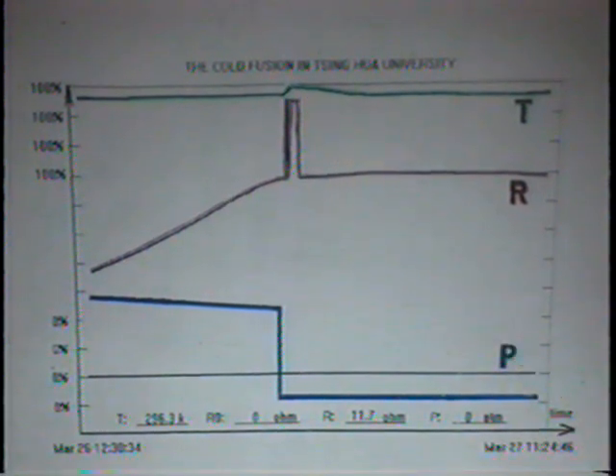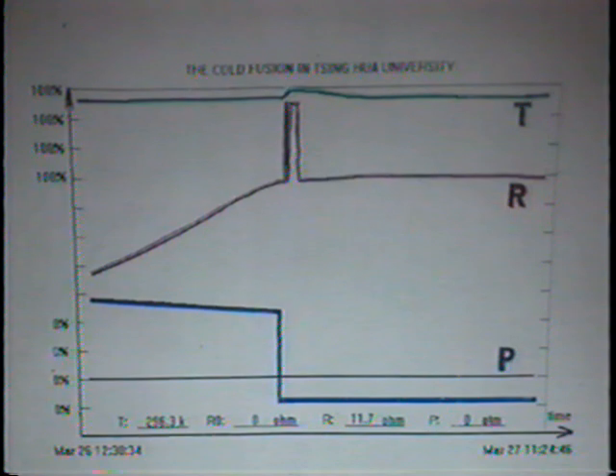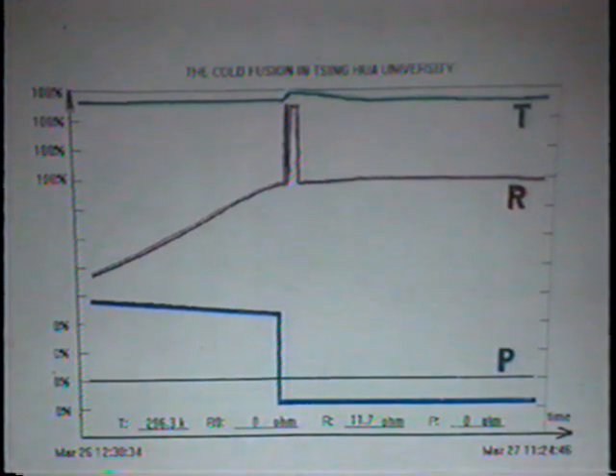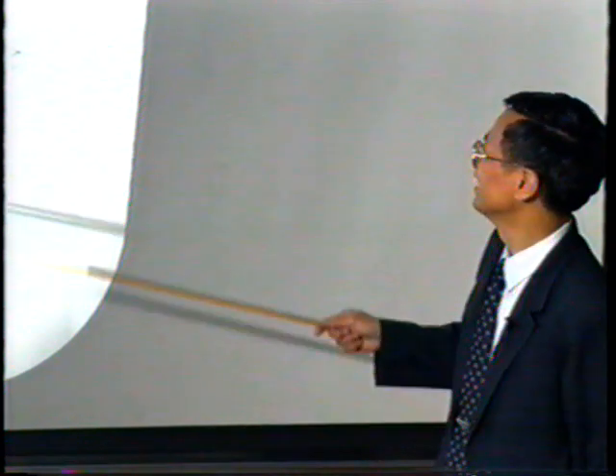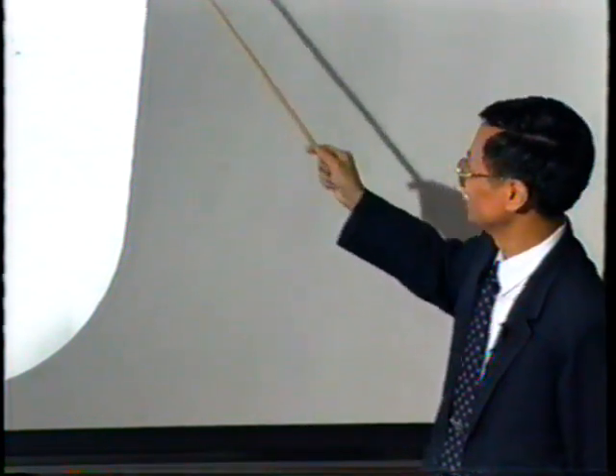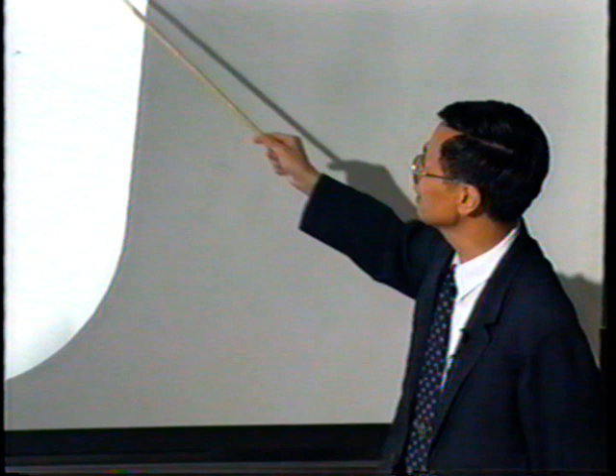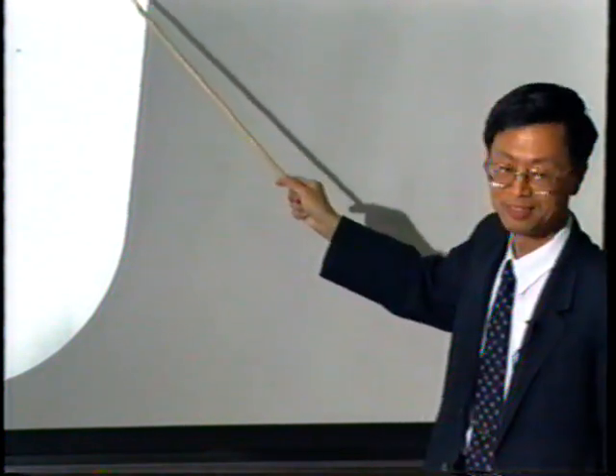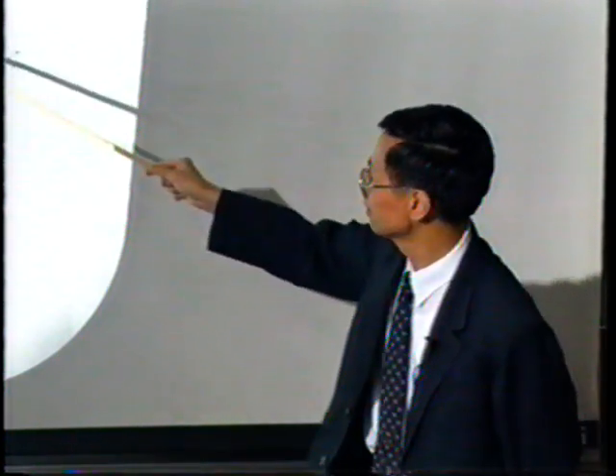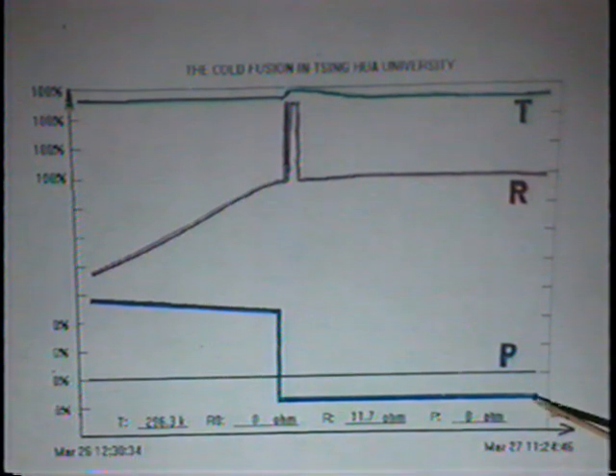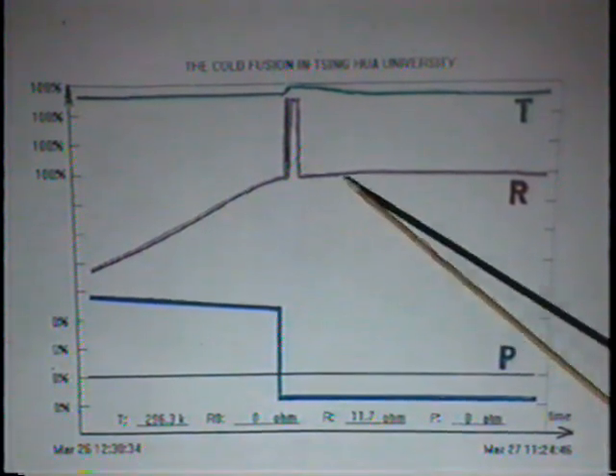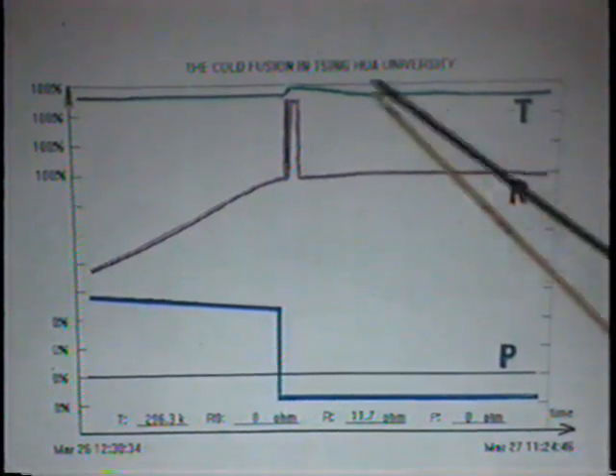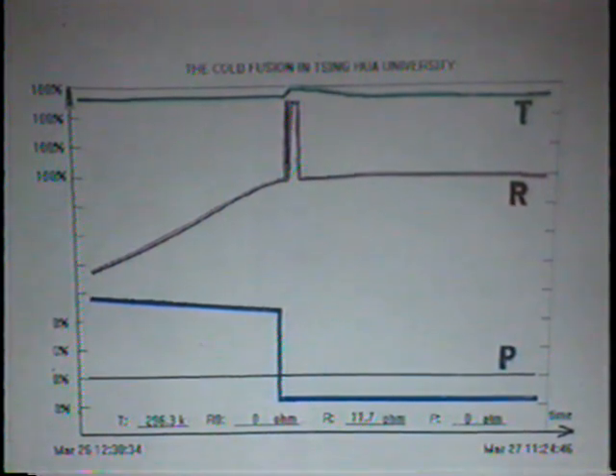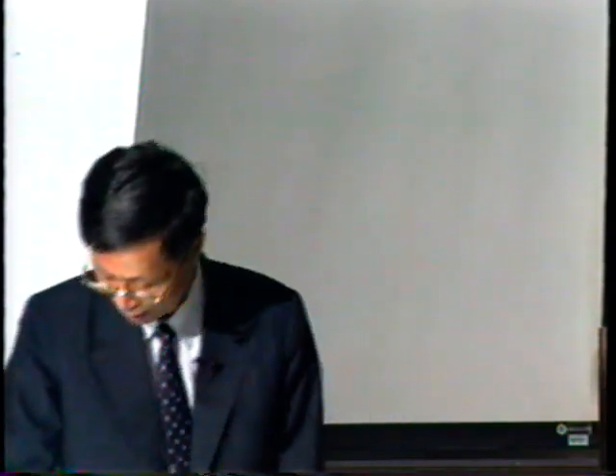Then the resistance will increase due to the temperature. So we try to see what the effect is for the degassing. If we start the discharge, the gas will leave. Then we think there will be an effect on the loading, an effect on the resistance. But it didn't appear. You see, the pressure goes down after the discharge. The resistance does not change very much when the temperature goes back. Then we say that's for degassing. What's the effect on the loading?